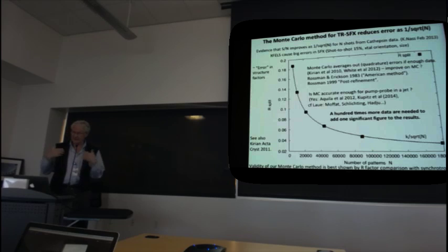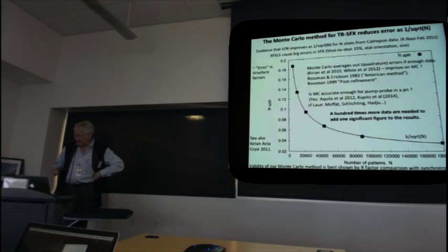And then if you simply add all the Bragg reflections from different crystals together, you'll average over size, you'll hopefully get enough sampling across the angular rocking curve to give you an estimate of the area of the profile of the spot, and you'll average over the shot-to-shot variations. So the idea of the Monte Carlo method, which we started with, was Rick Kirian's PhD, was just to average over all of those fluctuations by adding all the data together.